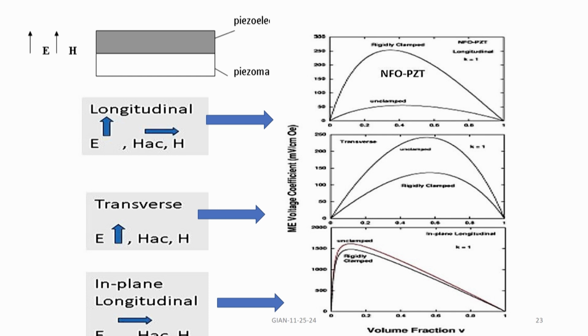So, we are considering a bilayer of a ferromagnet and a ferroelectric. So, these theoretical curves are for the ferromagnetic phase being a spinel ferrite, in this case a nickel ferrite. The ferroelectric phase is PZT. There are known parameters. You can estimate the Q values and D values which are given in the literature, or you can take the measured values and come up with these theoretical estimates.